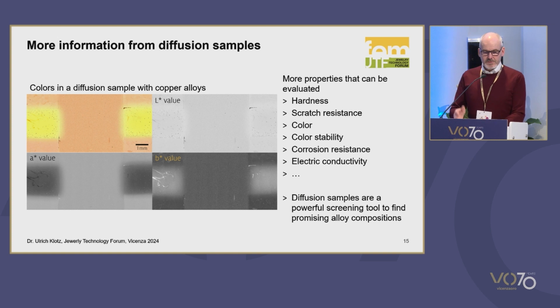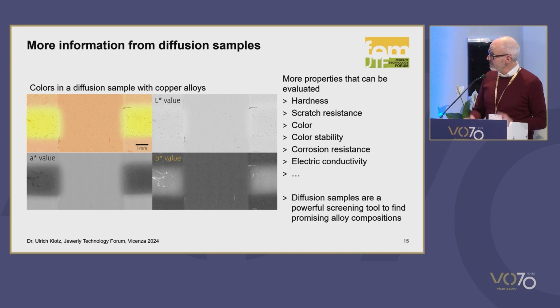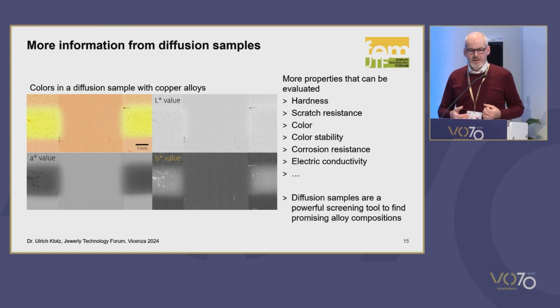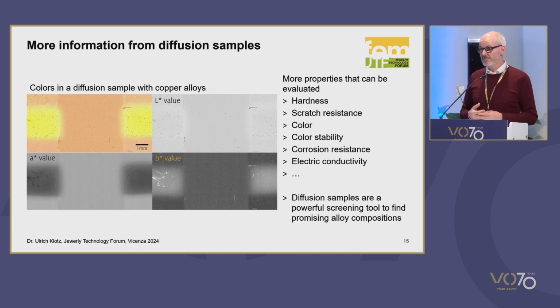We can also get more information from these diffusion couples. So this diagram here, or pictures here, are showing on the upper left side the diffusion couple. So the 3 copper alloys, you can identify them from the different colors. And now just from the image, I can extract the color values, L, A, and B. So I can match the composition with the color. I can also match the composition with the color after a corrosion test. I can do scratch testing. I can measure the electric conductivity. So there is much more than just looking for hardness.